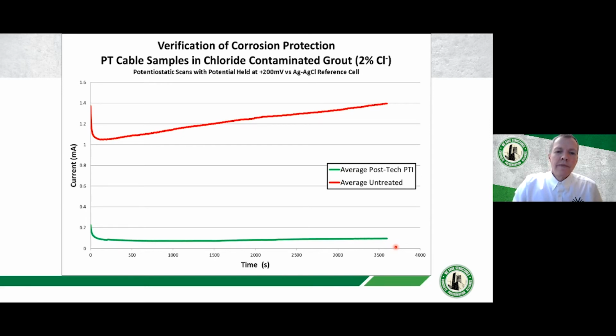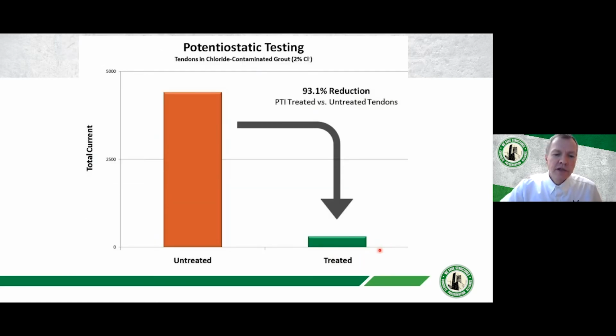You can summarize these charts by essentially calculating the area under each of those curves. And from that, you can basically get the total current or total charge passed. And you can compare the untreated samples to the treated samples, and you can see that there's a big reduction by doing the treatment on chloride contaminated samples in this case.